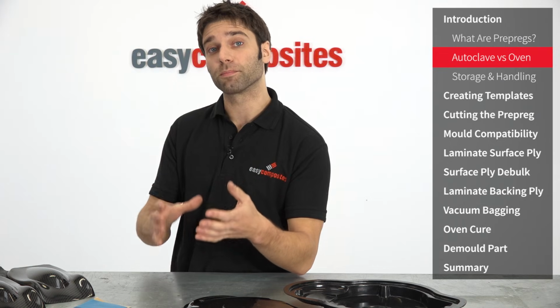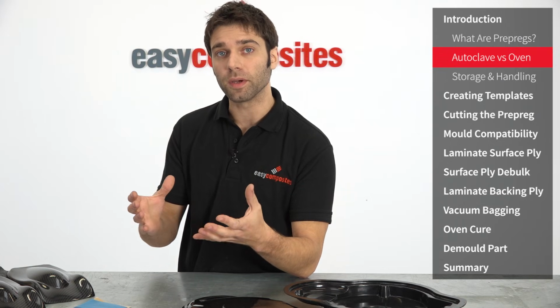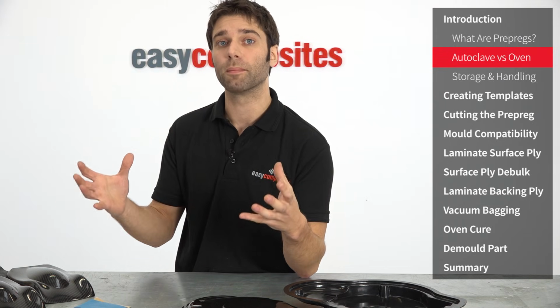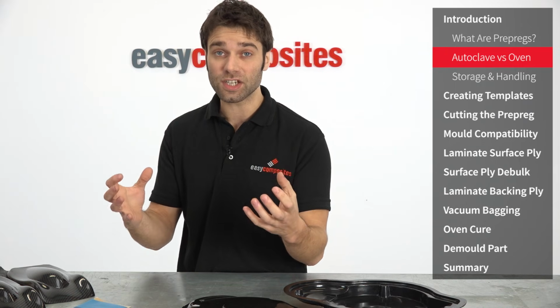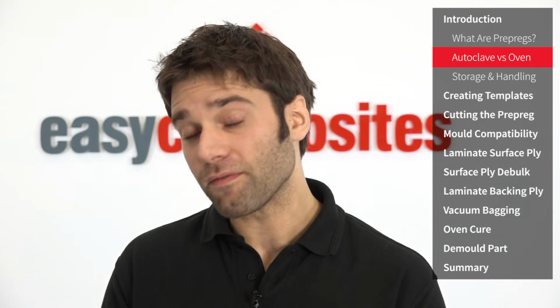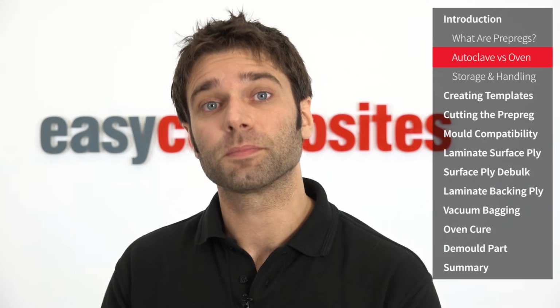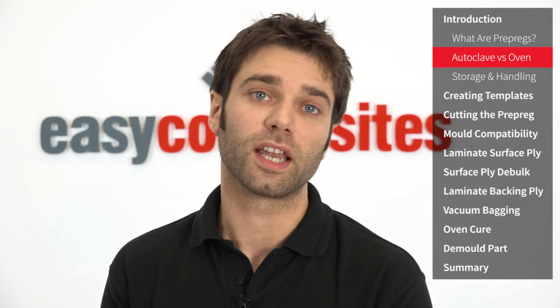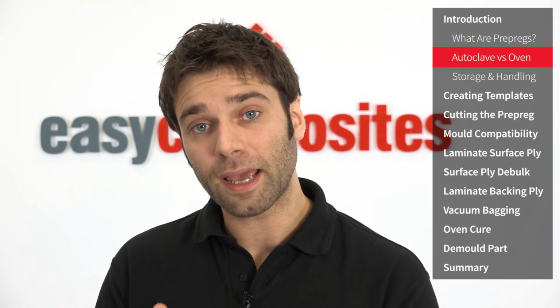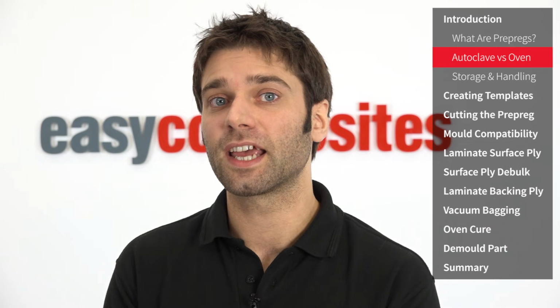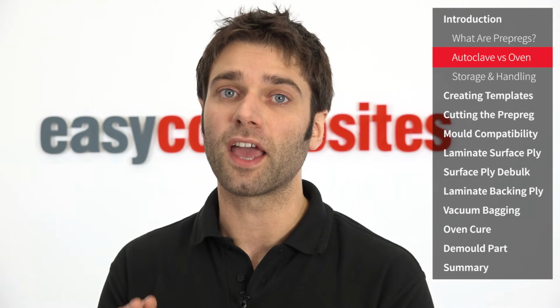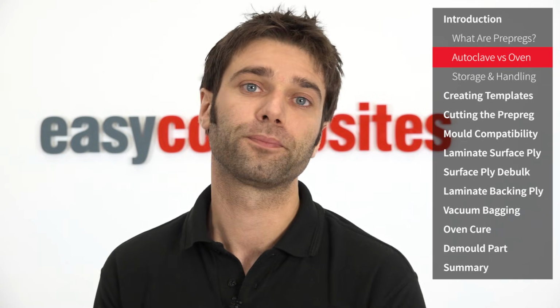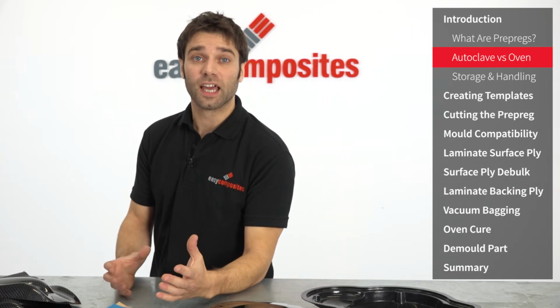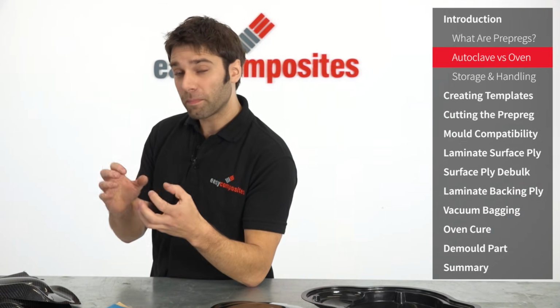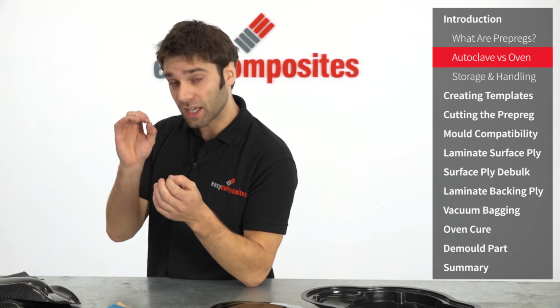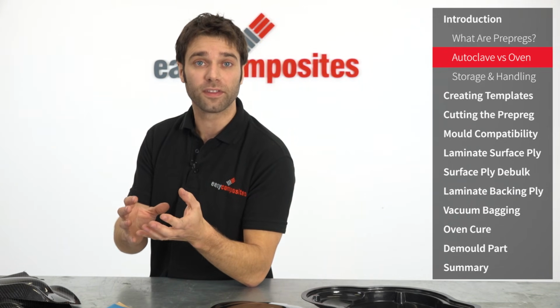There are two main methods of processing pre-pregs. The most common is to use a heavy piece of industrial equipment known as an autoclave. This is essentially a pressurised oven. However, gaining in popularity with the advancement of pre-preg technology are out-of-autoclave pre-pregs. These are laminated and vacuum bagged in exactly the same way as an autoclave system, however, they only need an oven to cure. If you're working without an autoclave, so just in an oven, one of the biggest challenges you'll face is to reduce the surface pinholes and the void content.